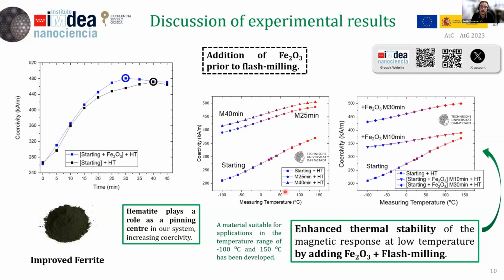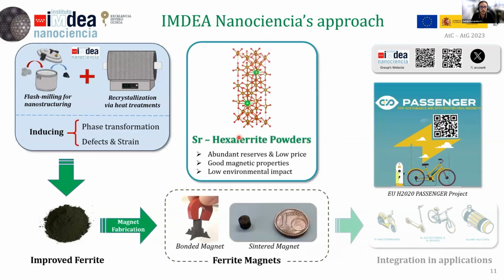Here you can see, even more so in the case of the addition of hematite content prior to the flash milling, just by milling 10 minutes, we can reach a more stable response of these powders. So here we are enhancing the thermal stability of these powders just by adding a little bit of hematite and flash milling afterwards. So now we'll go to the magnet fabrication.